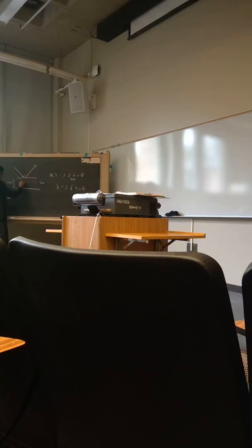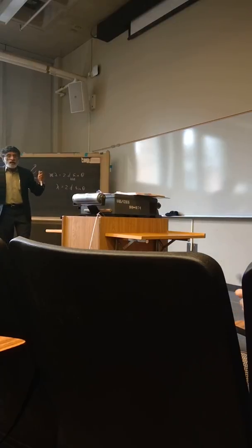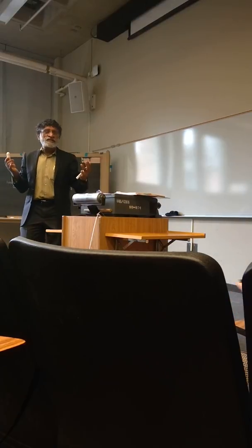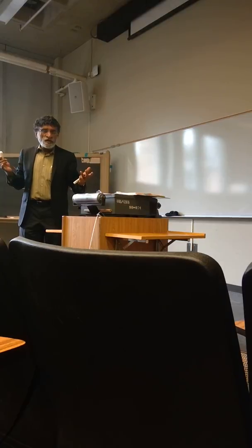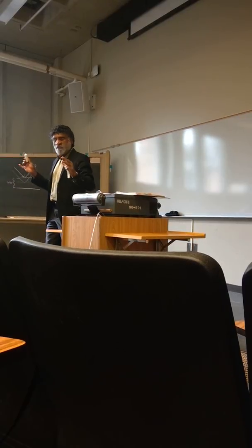You can have the diffraction from this. Basically, you can find an equivalent set of planes for this order. So this would have half the spacings. So this factor, you can change it. You can write this in general terms without the n, because if you do 1, 0, 0 and go to the second order, you find the 2, 0, 0 planes that have the corresponding diffraction. So we can drop this n and always say that we can find a higher order set of planes that satisfies this.